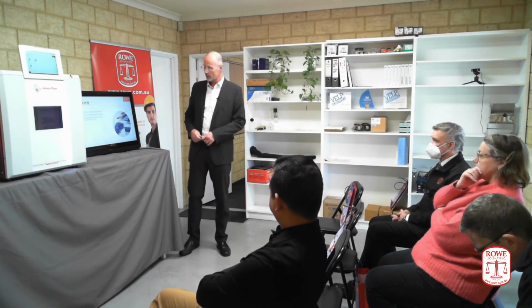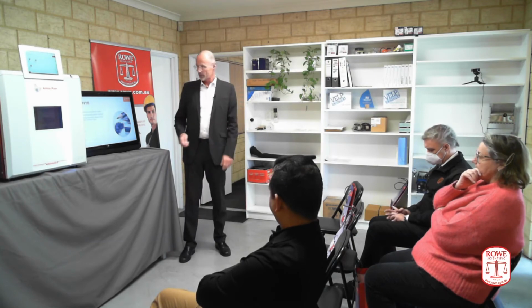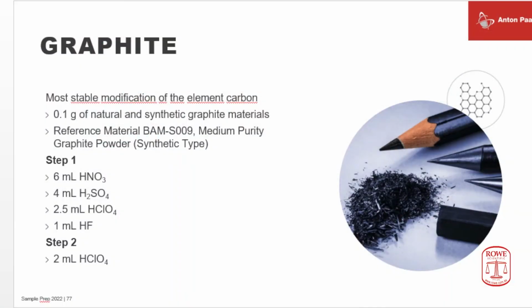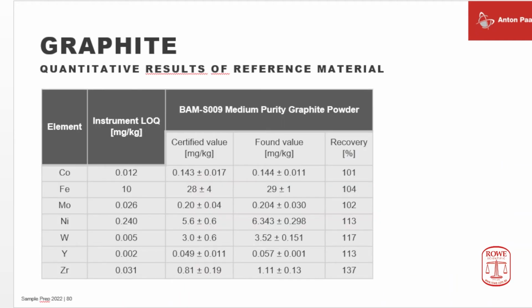Let's have a look at graphite. Like said before, it requires a two-step procedure. First, the 4-acid digest mix, and then a second step with the addition of perchloric, more perchloric for final oxidation. We are lucky that we have reference material for graphite. This is a German reference material, and you see certified values compared to what we found after the digest that I just showed you, and we find very high recoveries, very good recoveries for the elements of interest.